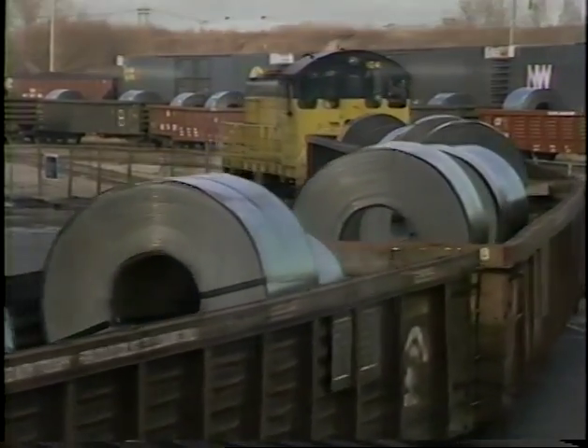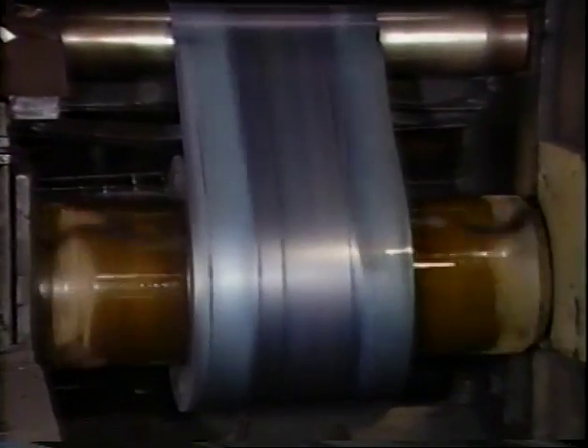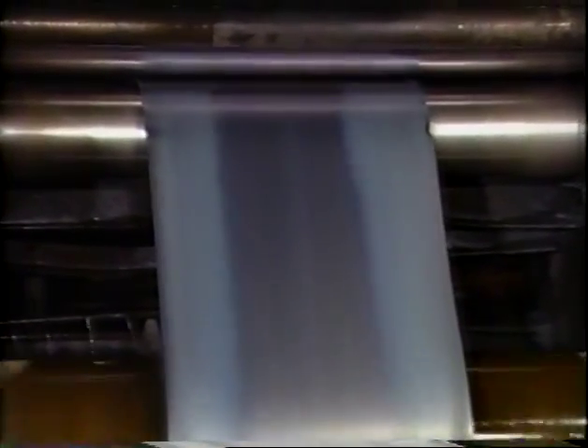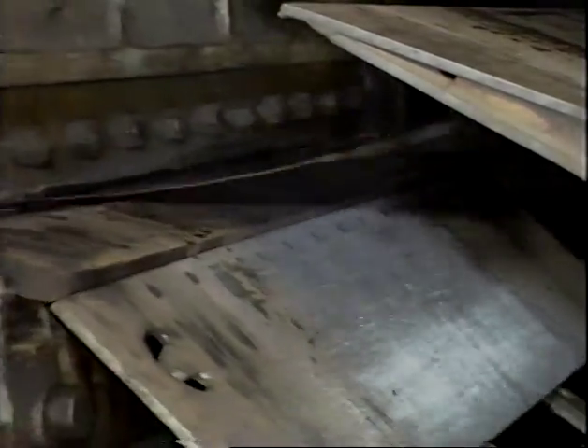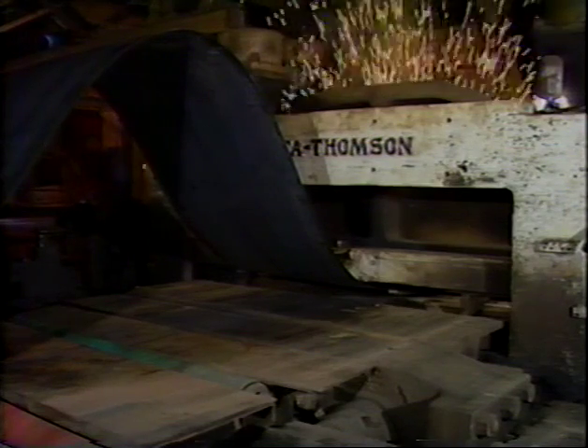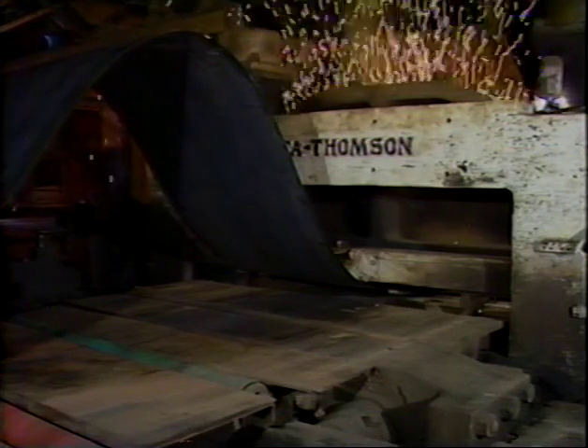When hot-rolled bands arrive at the Galvanized Products Division, their first stop is the continuous pickler. Top-quality galvanizing demands ultra-clean base metal for proper coating adherence, and the pickler's hydrochloric acid baths remove every trace of mill scale from the steel. Before a band hits the acid, its head end is sheared square and welded to the tail end of the preceding coil. A loop storage system feeds a continuous supply of steel into the acid tanks, where it's cleaned at a rate of 600 feet per minute.